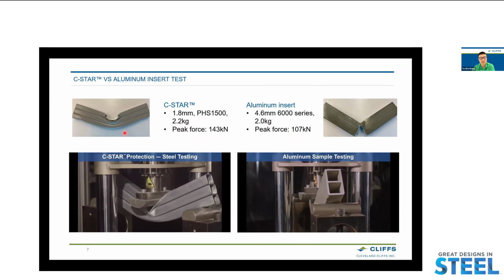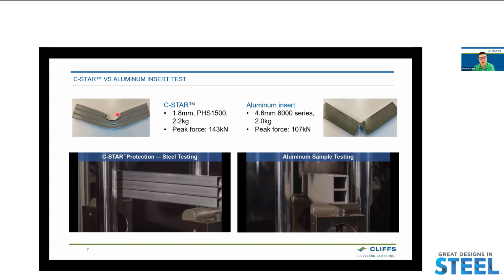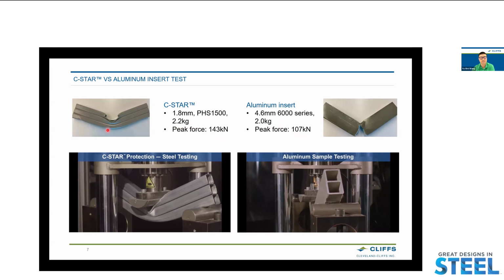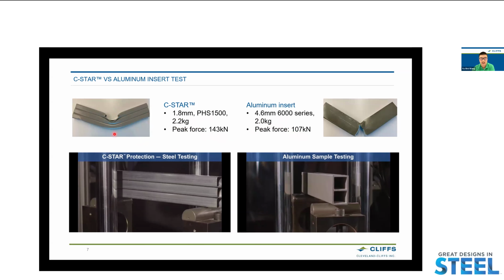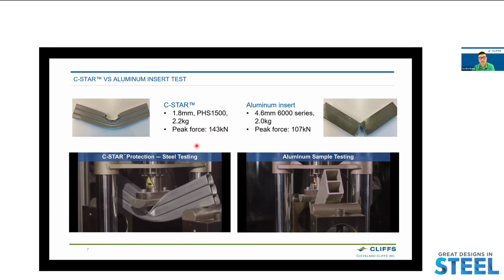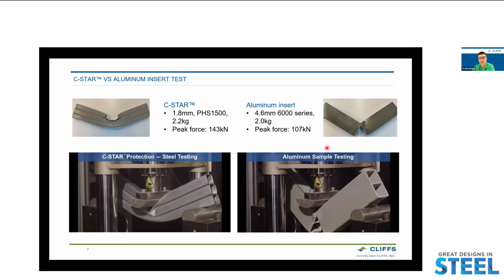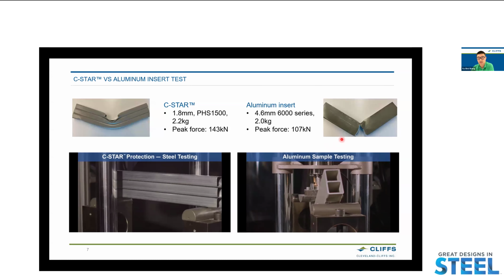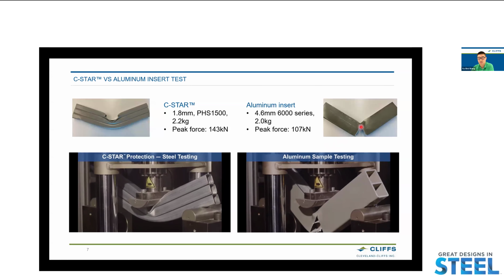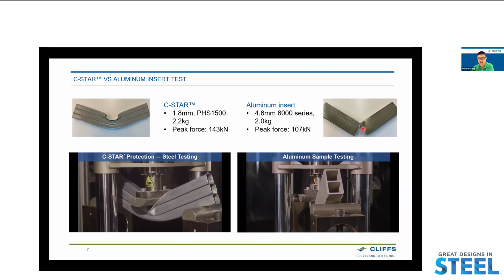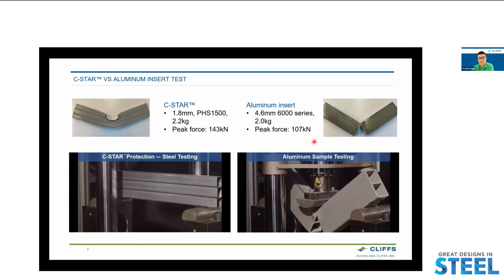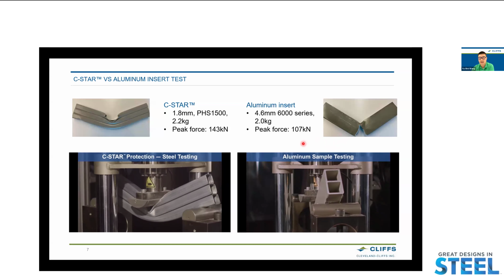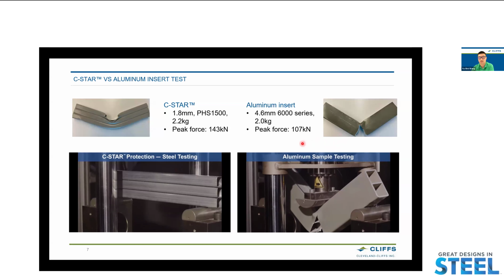So for C-STAR, we can see the indentation on the contact area. However, the overall structure maintains the integrity after the test. And we can tell from both the video and deformation picture that after the test, there's a crack across the whole section of the aluminum baseline. So this makes it lose the capability to maintain more load due to the characteristic of the material.